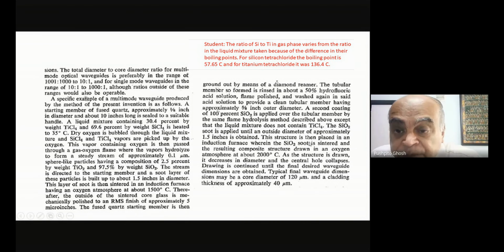Okay? This structure is then placed in an induction furnace wherein the SiO2 soot is sintered and the resulting composite structure drawn in an oxygen atmosphere at about 2000 degrees C. So they're repeating the process, but now they have actually applied two films over a glass rod which has been removed. Okay, the first film becoming the core and the second film becoming the cladding. As the structure is drawn, it decreases in diameter and the central hole collapses. Drawing is continued until the final desired waveguide dimensions are obtained. Typical final waveguide dimensions may be a core diameter of 120 micron and a cladding thickness of approximately 40 micron. So you've got some idea of what they are basically talking about.